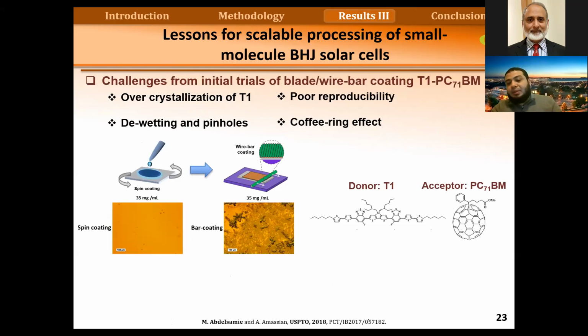So we try to apply this to larger scale areas. We try to compare spin coating here on the left with wire bar coating. Spin coating is a technique that wastes a lot of material. We add solutions, and when we spin the substrate, more than 90% of the solution is wasted. This kind of waste of material is difficult to apply in industry. But if we use other techniques like wire bar coating, blade coating, slot die coating, all of these techniques can be applied to large area.